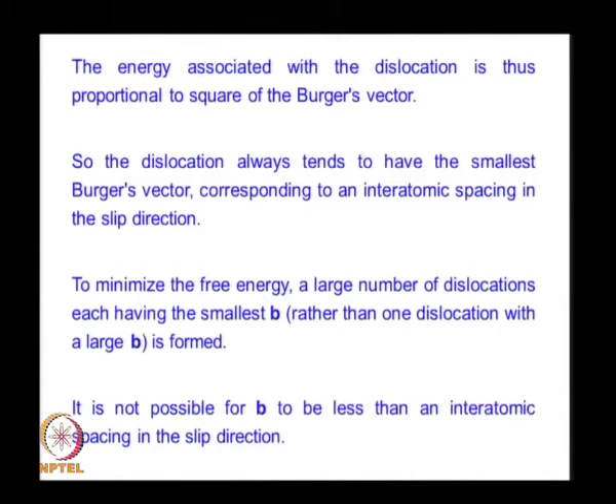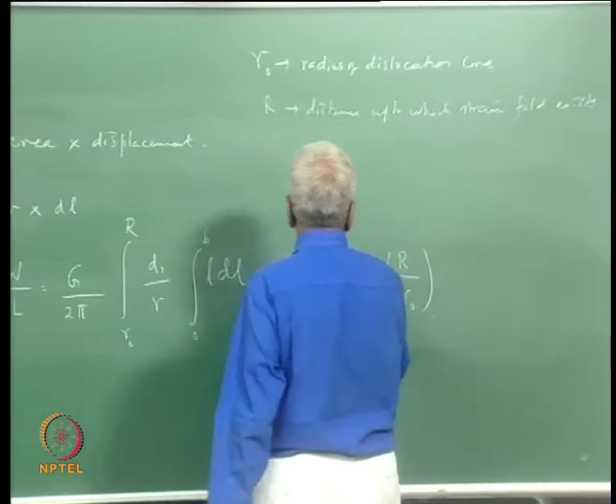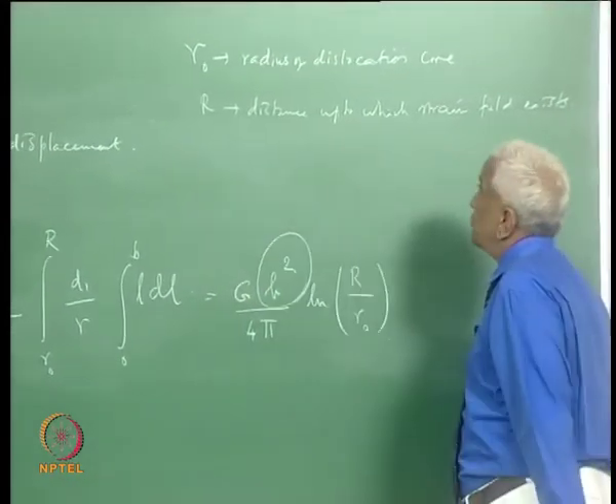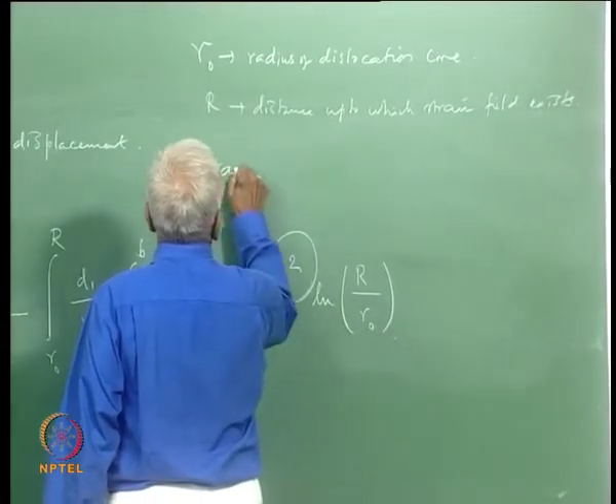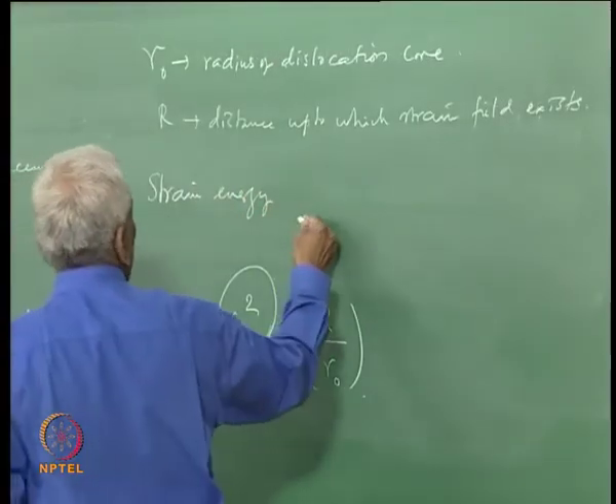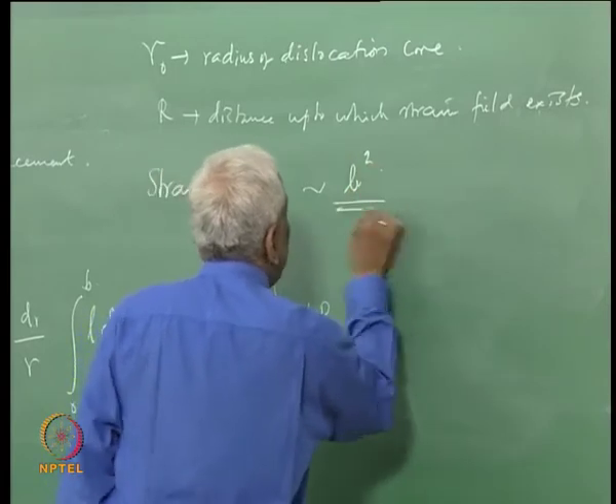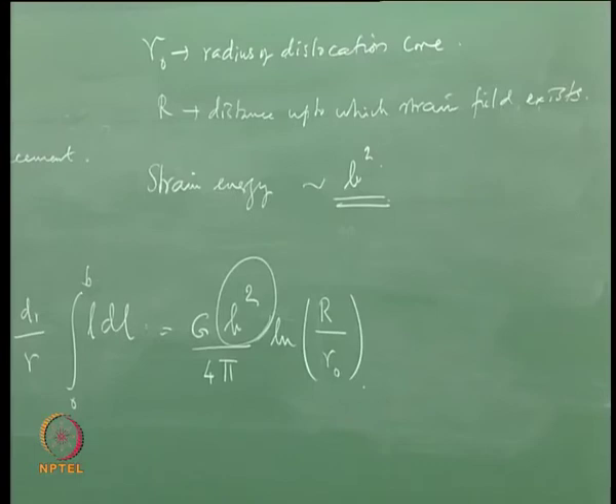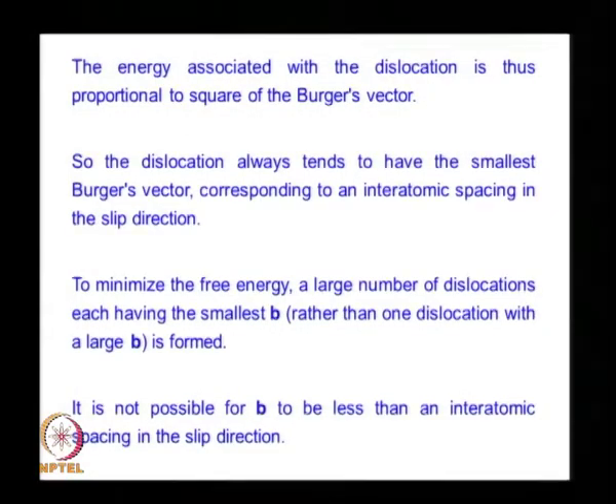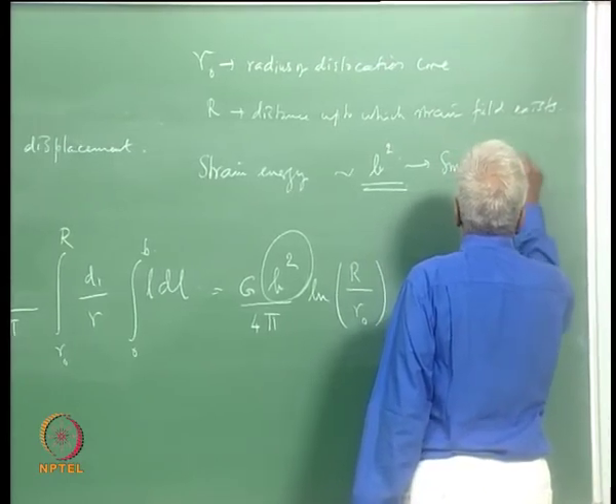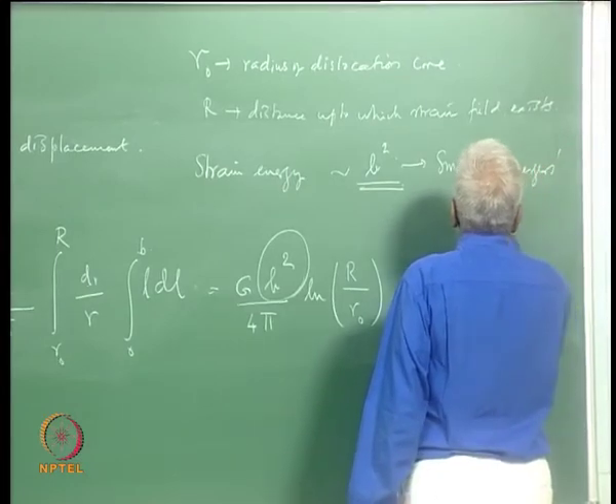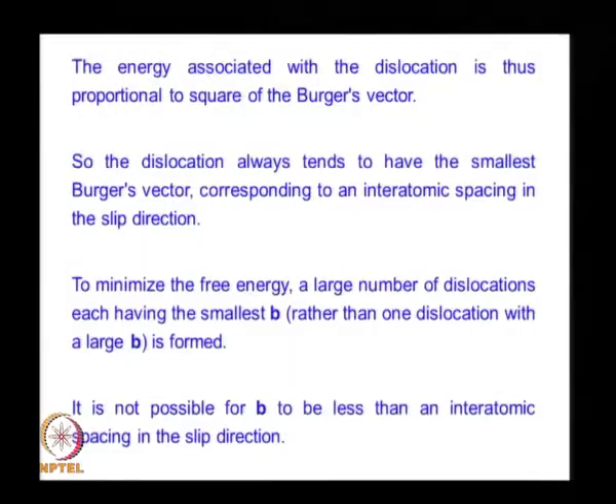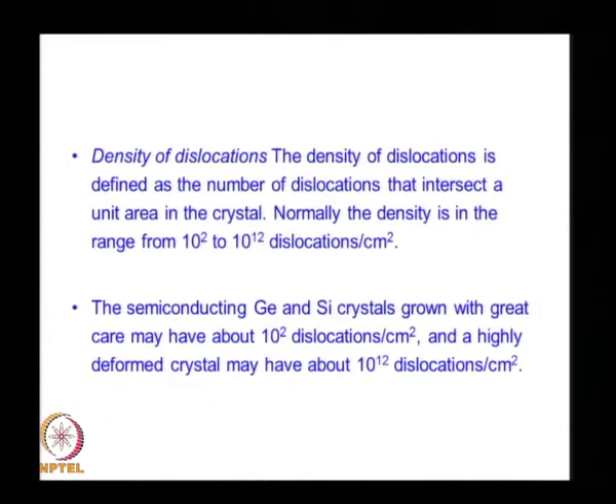So, we see that the strain energy, this total work, which is a measure of the strain energy, goes as the square of the Burgers vector. So, the strain energy associated with this dislocation goes as the square of the Burgers vector. So, the dislocation always therefore tends to have the smallest Burgers vector in order to minimize the energy. So, the free energy is minimized by having a large number of dislocations with small Burgers vector rather than one dislocation with a large Burgers vector. Of course, the Burgers vector cannot be smaller than one interatomic spacing.